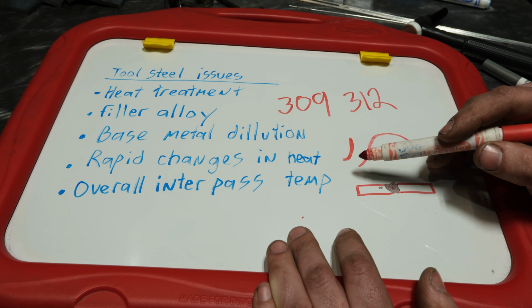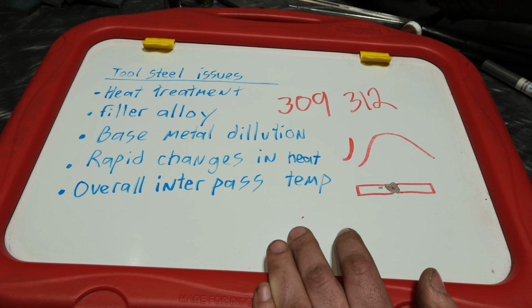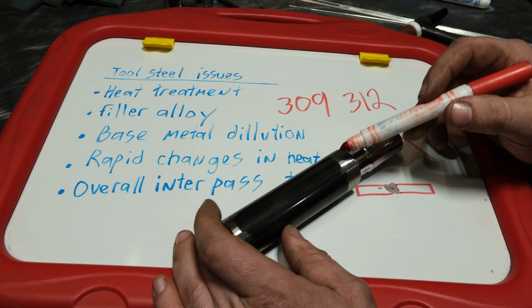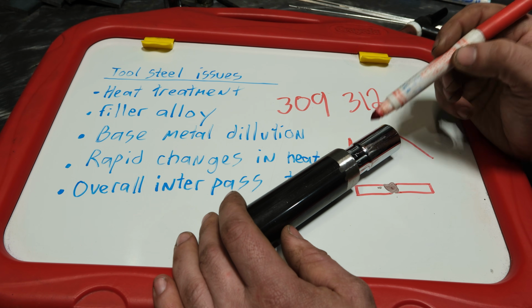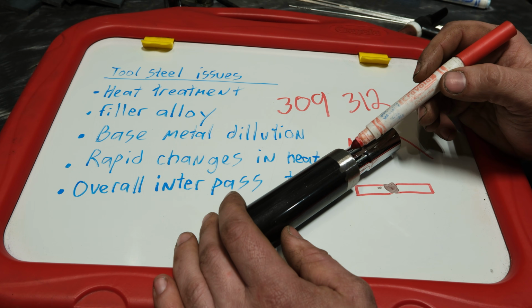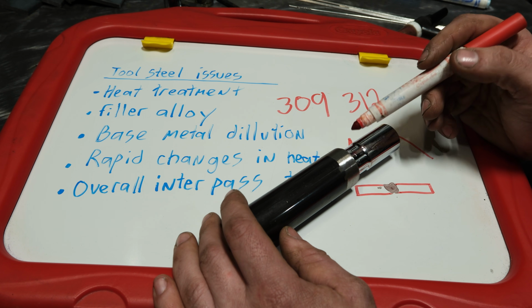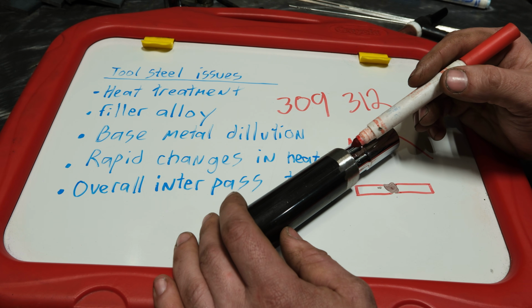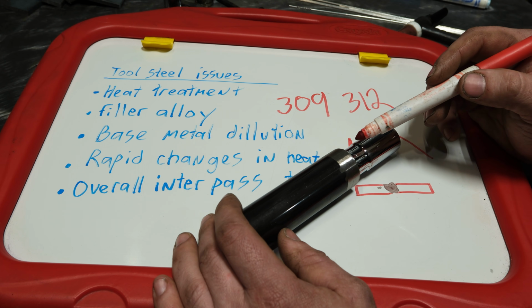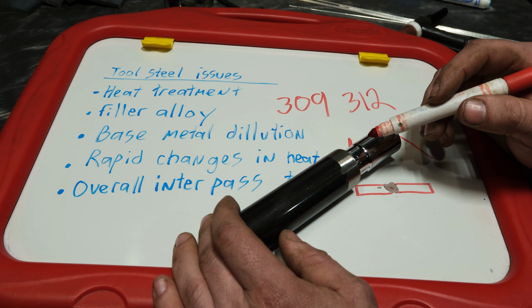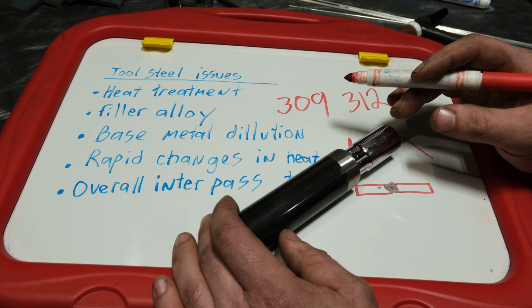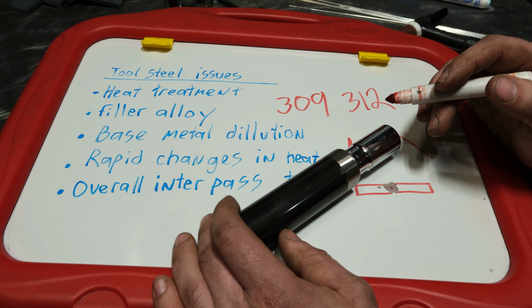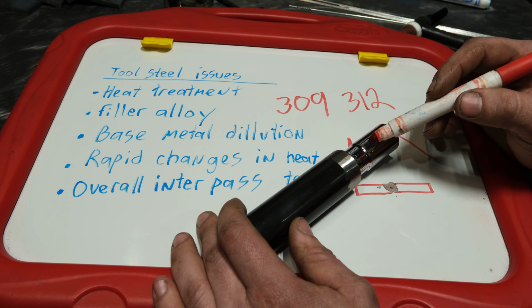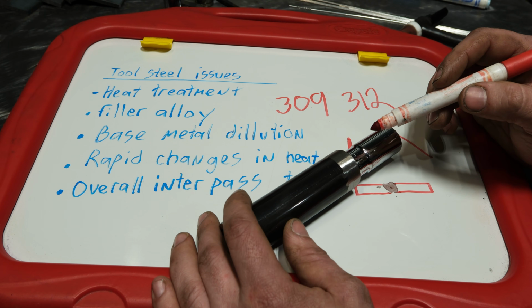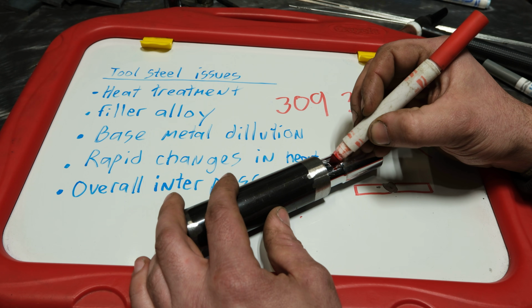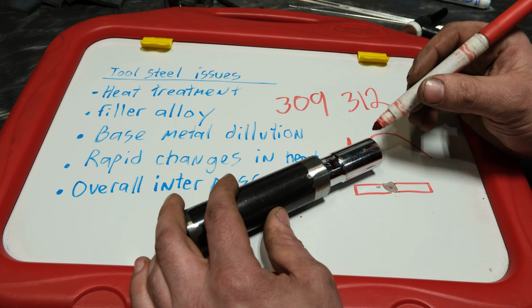You want to be mindful of how hot you actually get what you're welding. Like in the case of this thing right here, there's a lot of meat on this pipe, and I'm actually going to weld this later. And the socket has a fair amount of meat in it too. It would be very easy to do 5, 6, 7 passes of TIG, and I might be exaggerating a little bit there, but at least 3 passes to try and flush this sucker out in a hurry, and you think you're good. But what you need to understand is if you allow the temperature between your weld beads to exceed, I don't know, somewhere in the 600 to 700 degree area, where we'll just put it this way. If you weld on this so fast that this socket gets stupidly hot, what will happen is rather than affecting the heat treatment closer to the weld, you now could potentially affect the heat treatment in this whole socket,